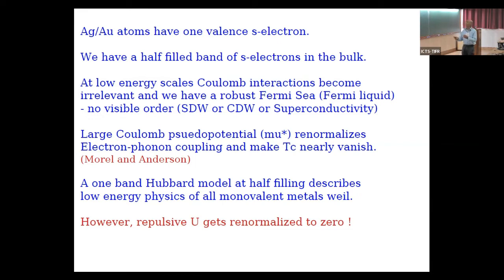So let us try to understand gold and silver. It's well known that both silver and gold never become superconducting. People have gone to the lowest temperature possible. That was always a puzzle. And people like Morel and Anderson rationalized it by saying that long-range Coulomb interaction comes into play, and because of retardation effects and so on, the effective electron-phonon coupling gets renormalized down by what is called the Coulomb pseudopotential. And they gave a theory which says TC will be very small or vanishingly small. But I was never happy with that theory.